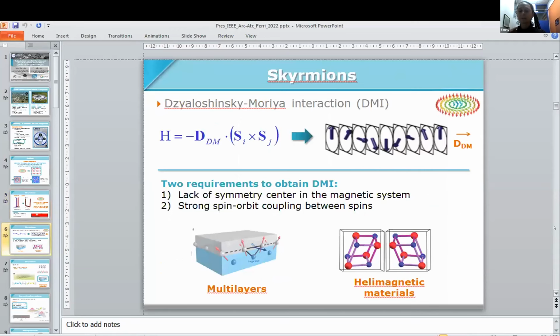This interaction, what is important is that it's a non-collinear interaction. So at the end, you have an exchange between one neighbor and the other, but you have a helicoidal precession of the magnetization. And to have a system where you have this DMI interaction, normally you should have a lack of symmetry center in the magnetic system and a strong spin-orbit coupling between the spins. You can achieve this through multi-layers, having a heavy metal and a ferromagnetic material in contact, and then you will have an interfacial Dzyaloshinskii-Moriya interaction. Or in bulk, if you have noncentrosymmetric materials, the crystalline structure has a lack of symmetry, and so you can have it directly in bulk. So here we will focus on multi-layers.